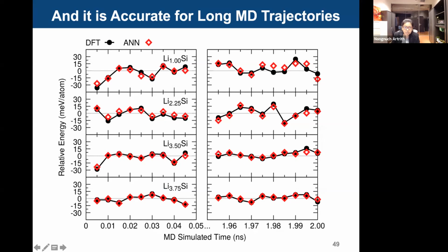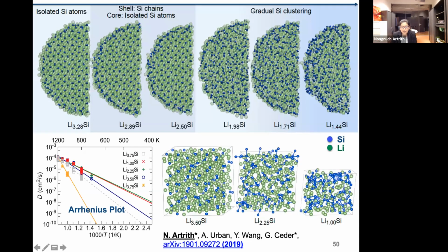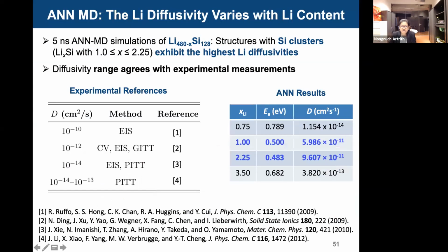So many different compositions. This is just one neural potential, but it can describe many different compositions, like you can see many different lithium concentrations. So the neural potential can predict really excellent and good agreement with the DFT reference data. And we use neural potentials in simulations with many different types of structures, nanoparticles, and many different phases in the structures, and also many different temperatures. And then later we predict the diffusivities using Arrhenius plots, and then convert to conductivities and also activation energies. And here, this table summarizes our predictions of 4 different compositions of lithium in the structures.